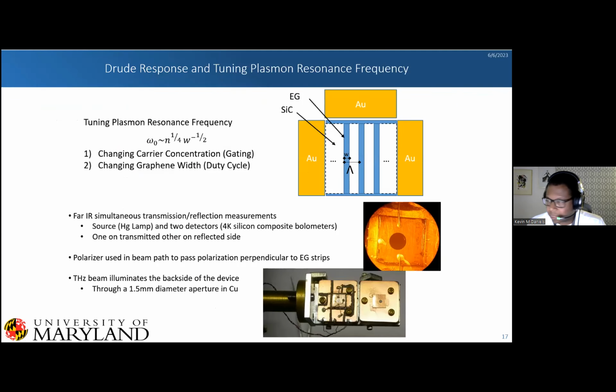So this is our setup here. This is a much simplified equation, just saying that our plasmon resonance frequency goes with our carrier concentration to the power of 1/4, and with the width of our ribbons to the power of -1/2. And so the two things that we can control, because again our carrier concentration is set, are the carrier concentration through gating, and then changing the duty cycle or the width of our graphene.